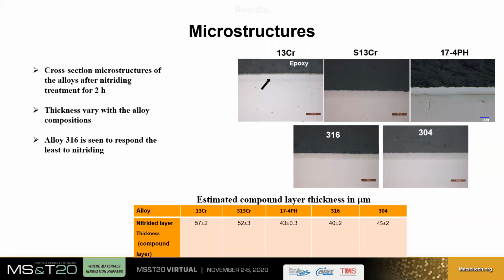Okay, now let's discuss the results of the study. After nitriding, samples were evaluated for nitriding depth. As we can see from this microstructure, there is formation of a continuous layer of chrome nitride with traces of iron nitride, which is well established in literature: on these stainless steels during nitriding, we form predominantly chromium nitride and traces of iron nitride. That is established by X-ray diffraction study.